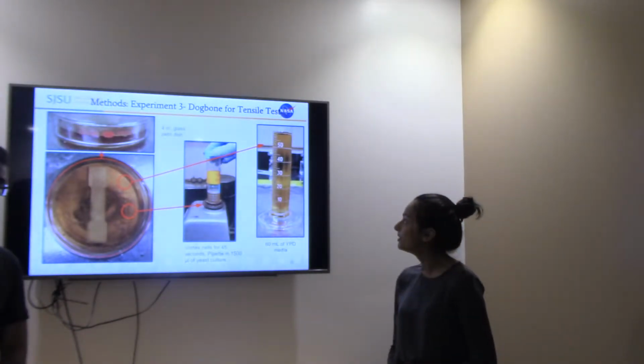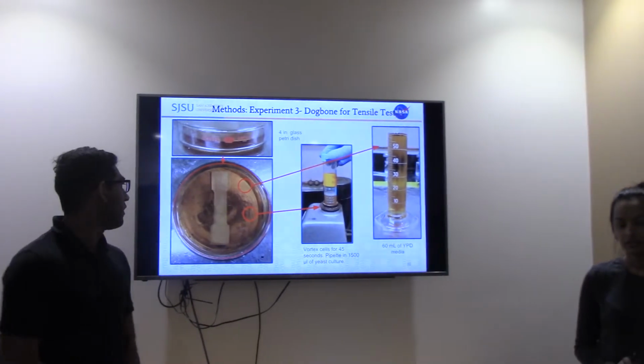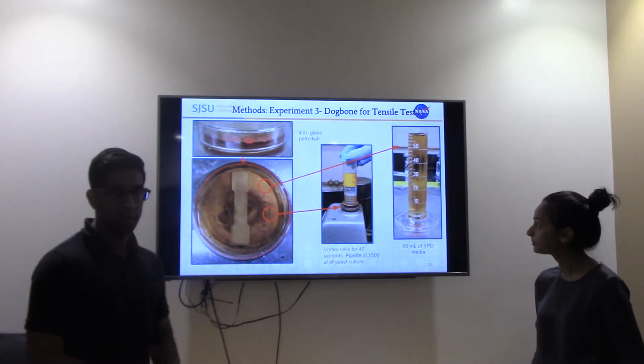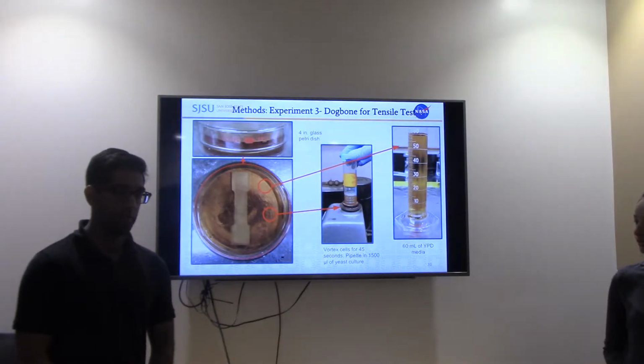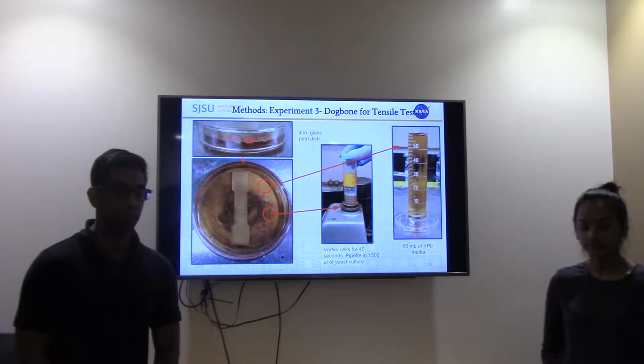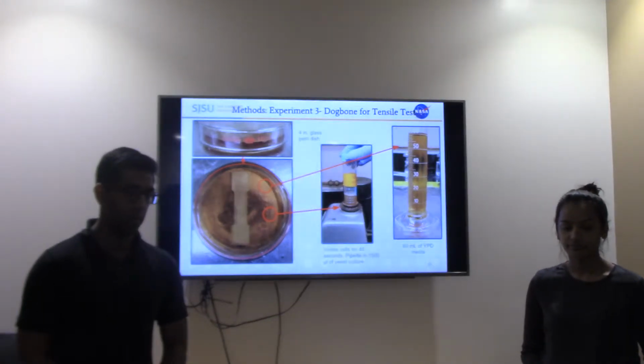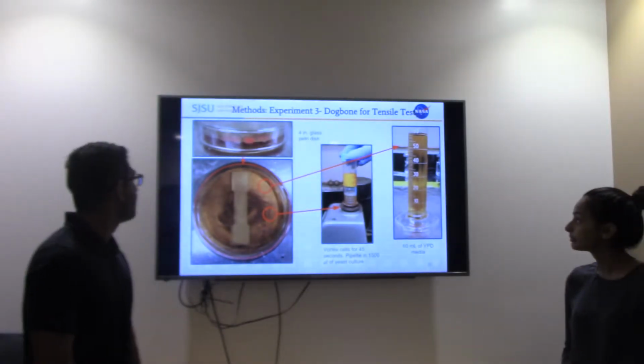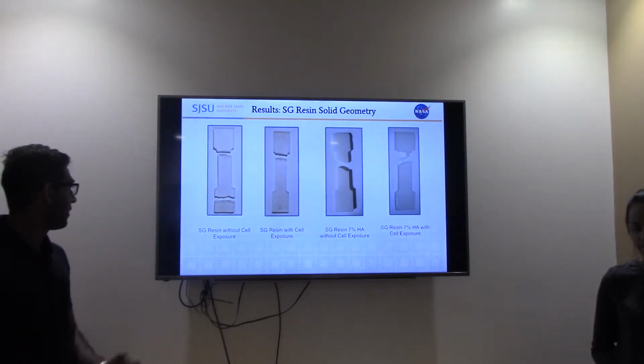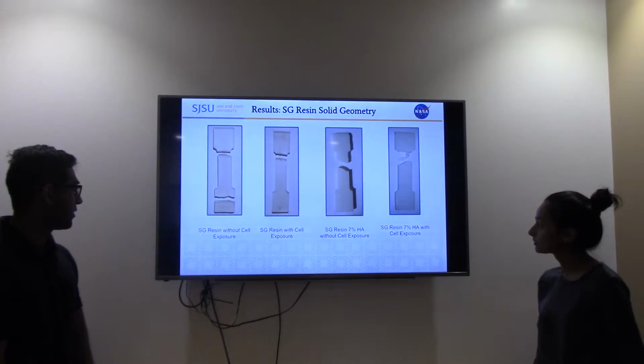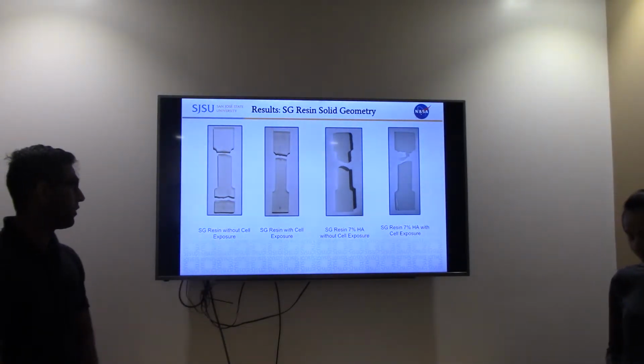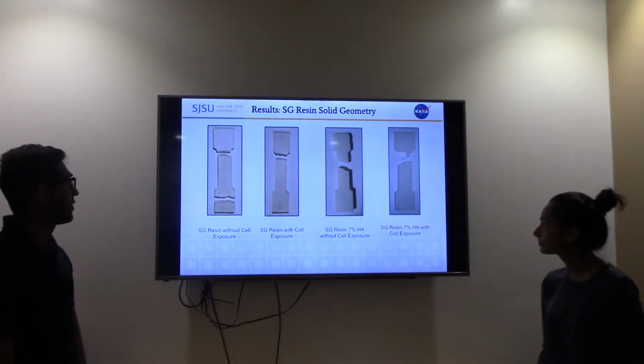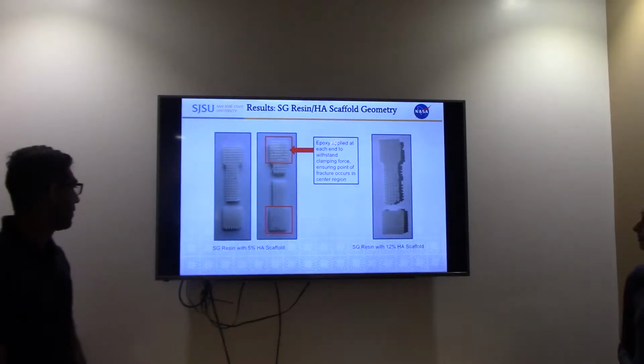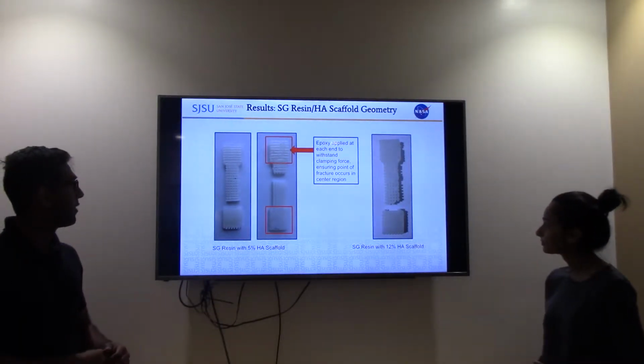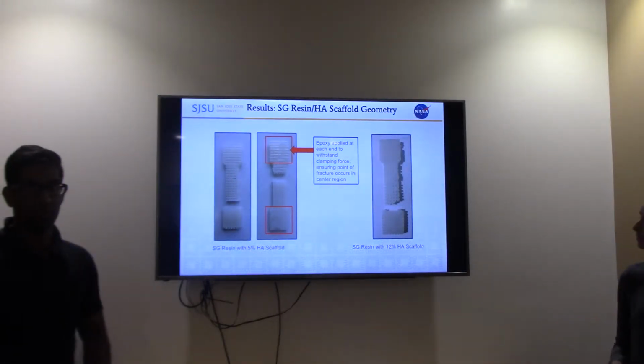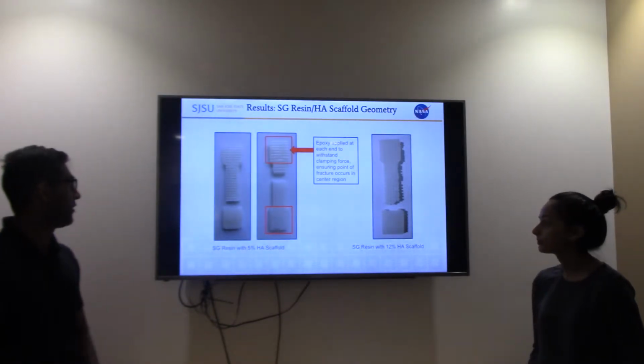For the next part of the experiment, we fabricated these dog bone shapes for tensile testing. They're made of the same materials, and then we submerged them in YPD media in petri dishes and pipetted in 1,500 microliters of yeast culture after vortexing them for 45 seconds to evenly disperse all the cells. Here are the results of some of our tensile tests. We have the SG resin without and with cell exposure to see if there were any differences. And then we have the 7% HA nanoparticle resin with and without cell exposure. And here we have the scaffold models where we had 5% HA, and we had to apply epoxy on the 2 ends of the dog bones to make sure it withstands the clamping force of the tensile test, so the fracture occurs in the center region.